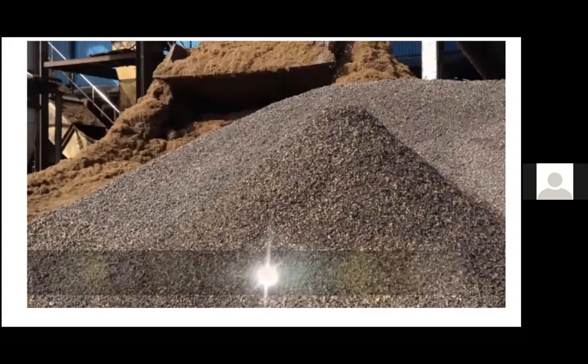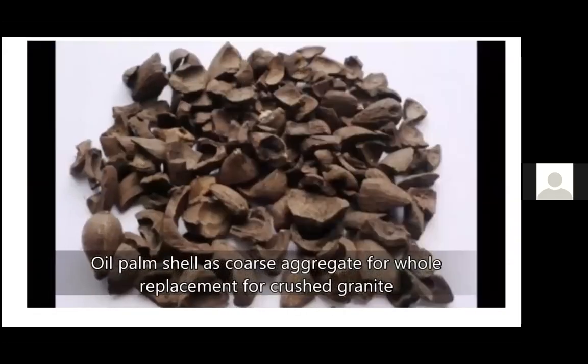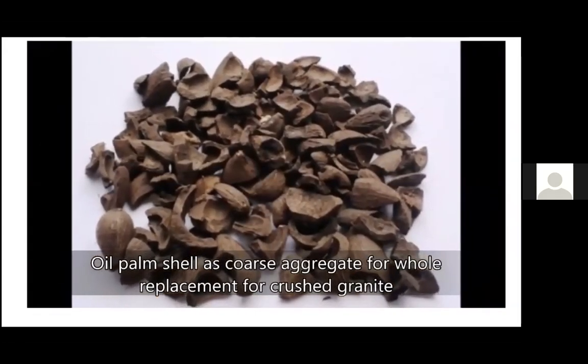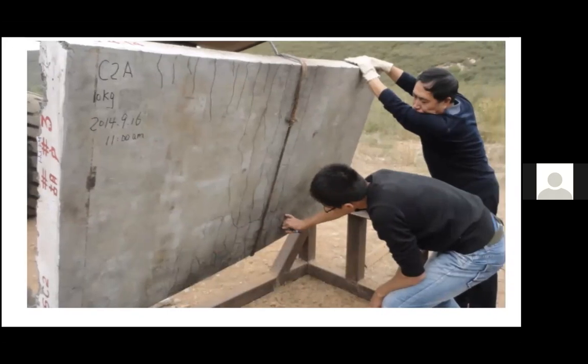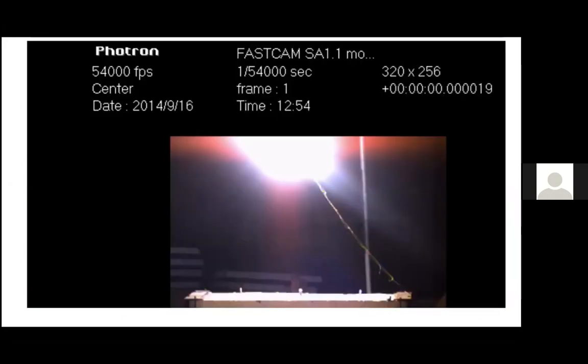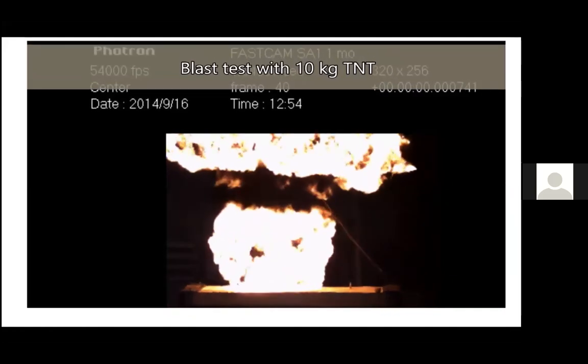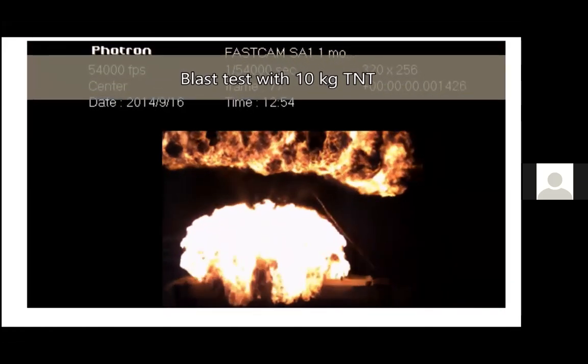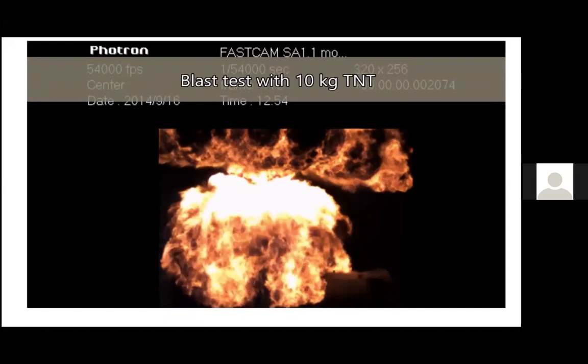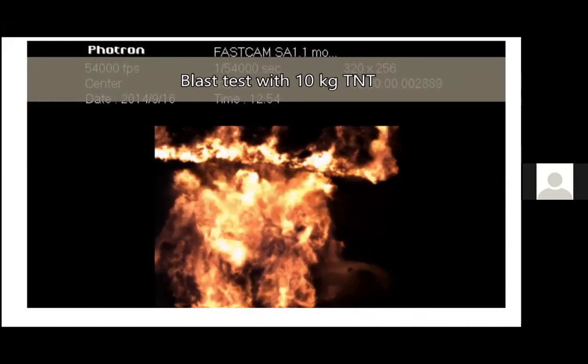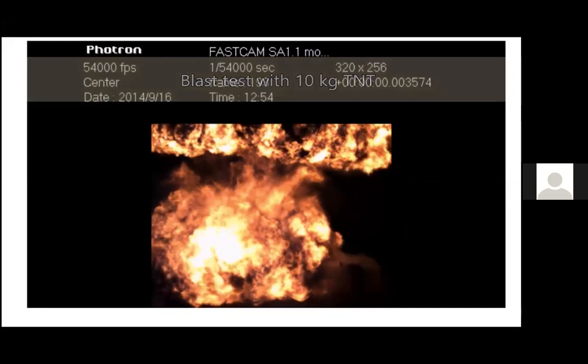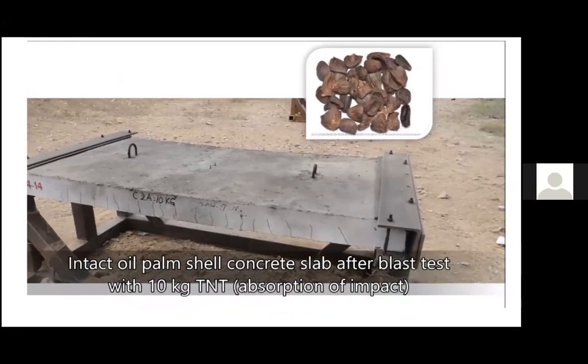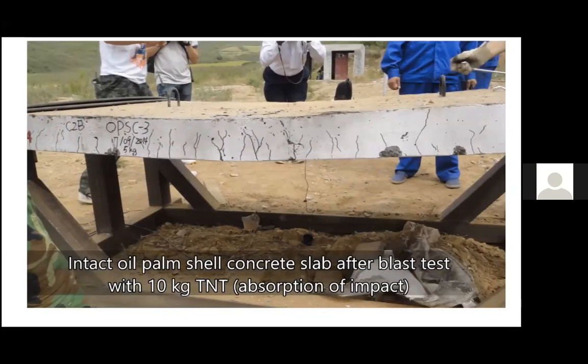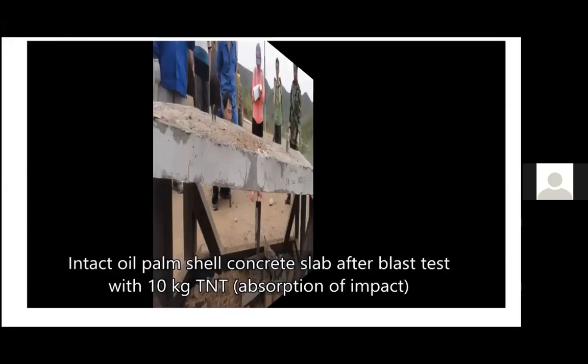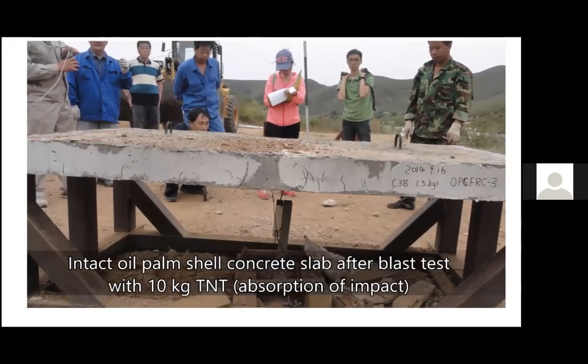This is the second slab that we made using the oil palm shell concrete, a lightweight slab. See, this is after the blast, with the same 10 kg TNT. See the impact and the blast hitting the slab. But we can see that the slab is intact after the explosion. So what does it show? It means the slab is capable of resisting the impact, blast, and pressure. This is very interesting for us. The slab was intact even after this.